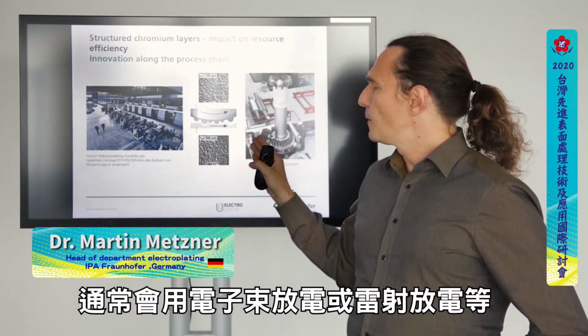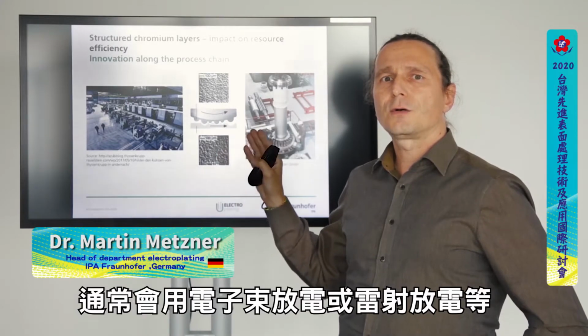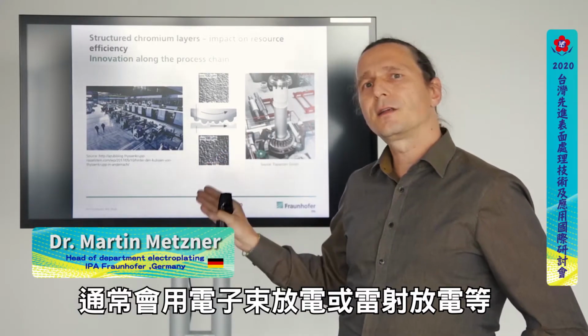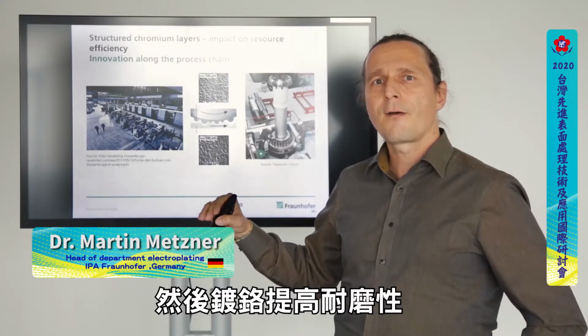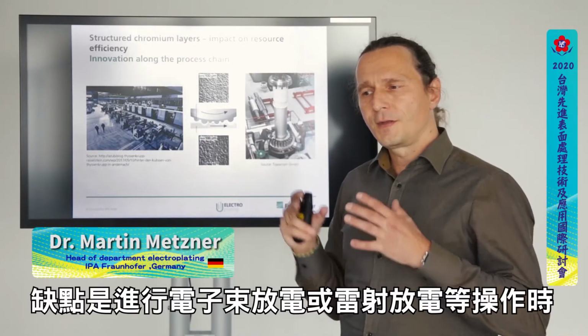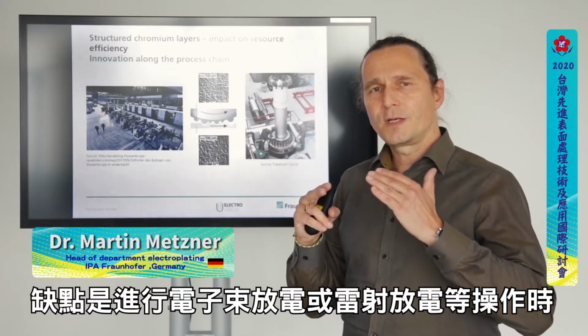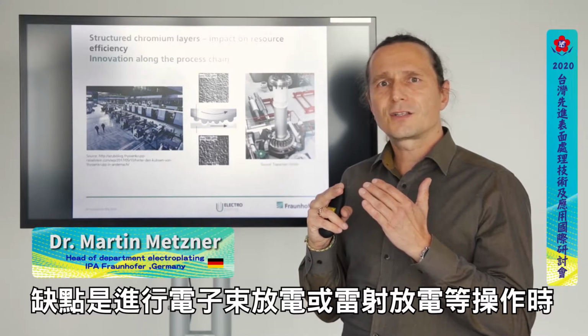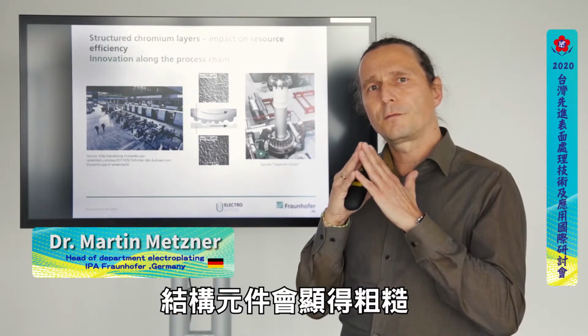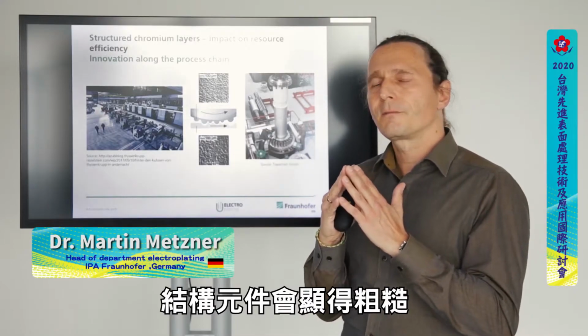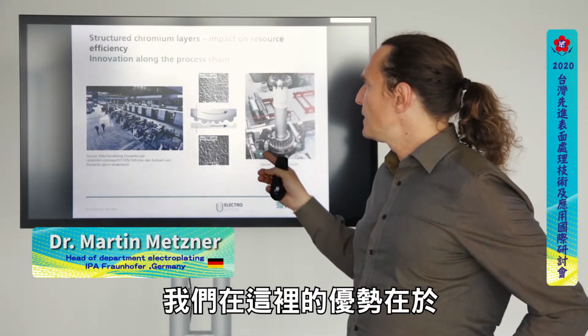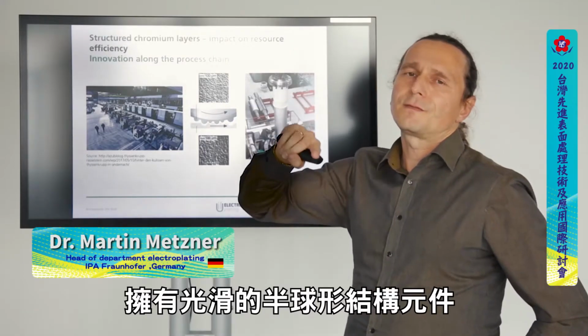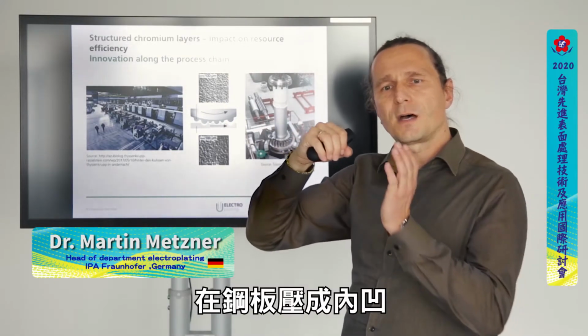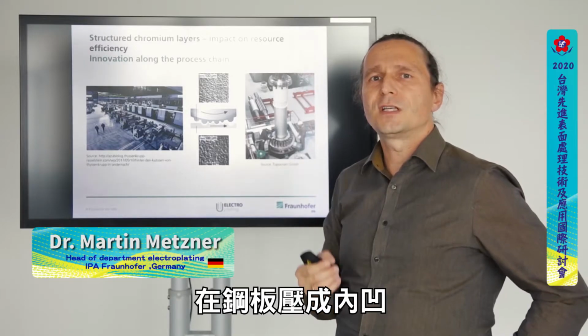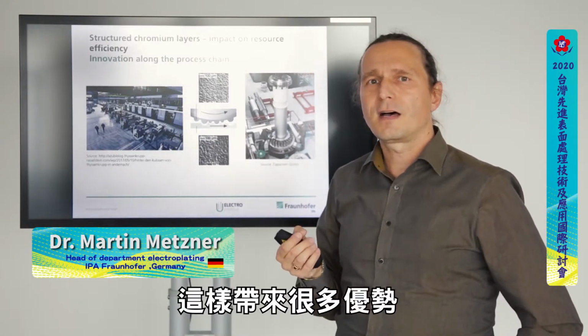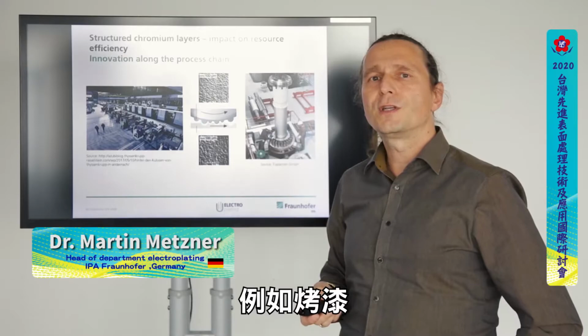Normally they do electron beam discharge or laser discharge or something like that, and do the chrome plating afterwards for the wear resistance. The disadvantage there is that when you do electro discharge or laser discharge, you always have rough structure elements. The advantage we have here is that we've got those smooth hemispheric structure elements which are pressed as a negative in the steel sheet, and this gives many advantages, for example, when you go into the painting.